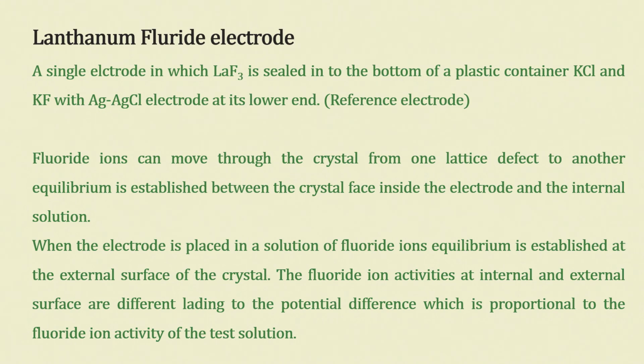Here is a single electrode in which lanthanum fluoride is sealed into the bottom of a plastic container containing KCl and KF with a silver chloride electrode at its lower end. So, silver chloride would be the reference electrode. So, fluoride ions can move through the crystal from one lattice defect to another lattice defect, and equilibrium will be established between the crystal face inside the electrode and the internal solution. So, when the electrode is placed in a solution of fluoride ions, equilibrium is established at the external surface of the crystal, and the fluoride ion activities at internal and external surface are different, leading to a potential difference which is proportional to the fluoride ion activity of the solution.